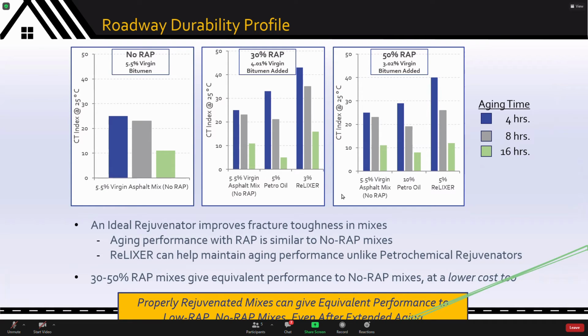You're measuring CT Index as a function of aging parameters, loose mix oven aging. Predictably, you can see the drop in properties as a function. This is a no RAP mix as a function of more and more aging on the roadway. We took this data and simply put it here and compared it to 2 cases, both with 30% RAP and 4% virgin bitumen. In case A, it was rejuvenated with 5% petrochemical oil, and in case B, it was rejuvenated with 3% ReLIXER. What you can see here is that the CT Index number is fairly comparable upon immediate manufacturing. However, as you age the mix, you can see that the aged CT Index number of the petrochemical dosed rejuvenated mix was not nearly as good as your control mix.